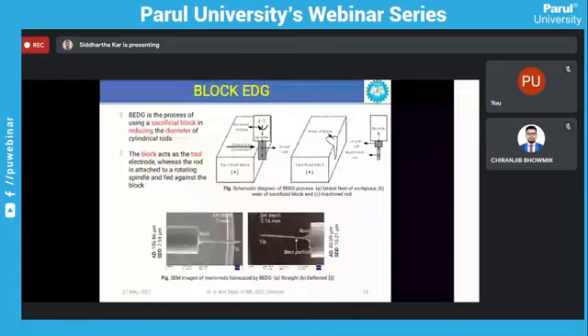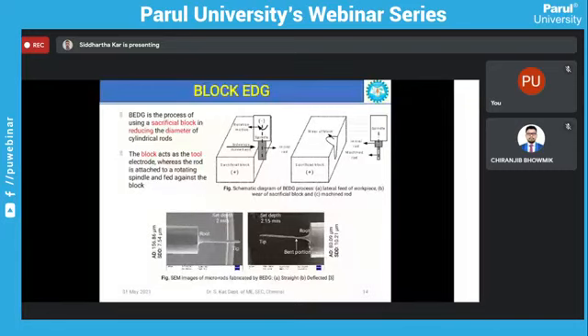So utilizing this technique, two micro rods have been fabricated. In the first one, that is the left hand side figure, a set depth of 2 mm is used. That means the rod is fed for a total depth of 2 mm against the block. Here we see that an average diameter of 156.86 micrometer is achieved, and the standard deviation in diameter, that is from the tip of the tool to the root of the tool, is 7.54 micrometer only. This suggests that block discharge grinding can be used to fabricate very precise micro rods.